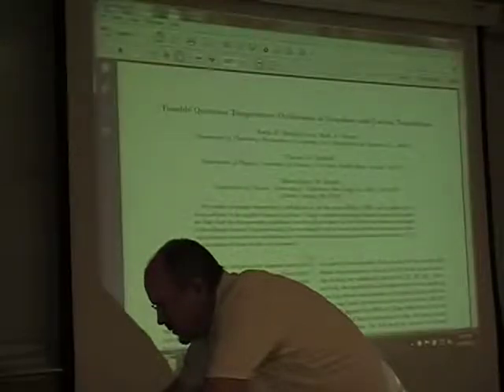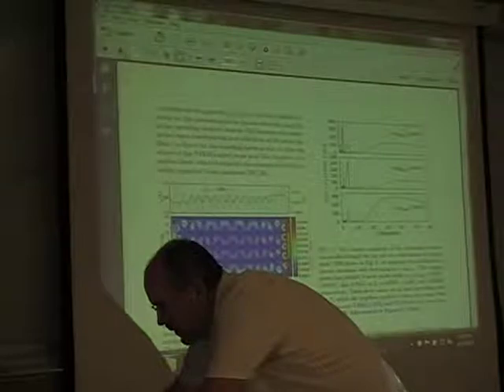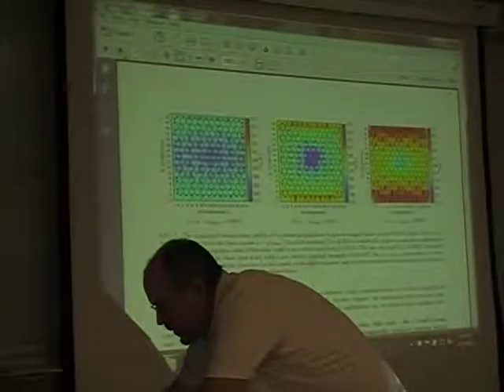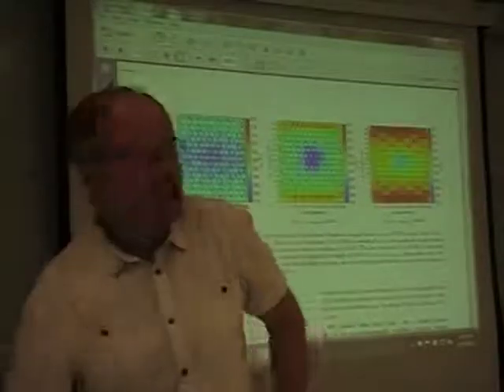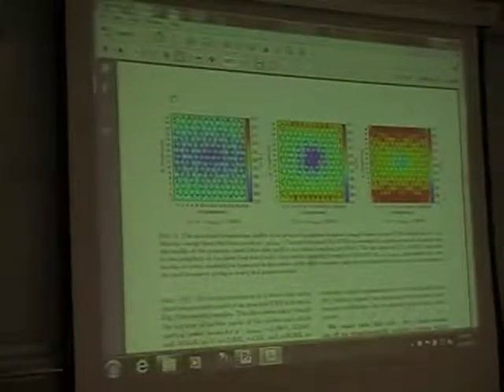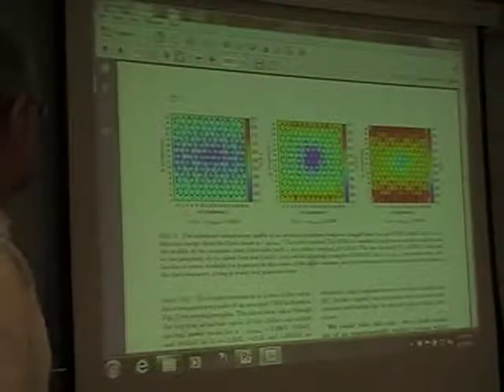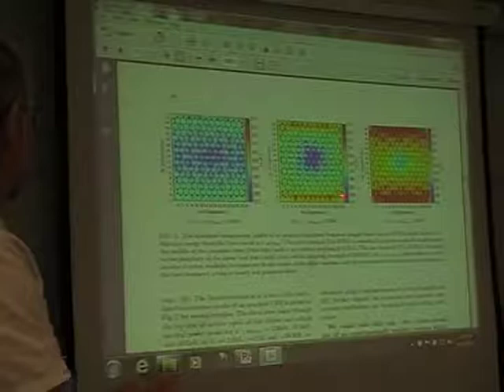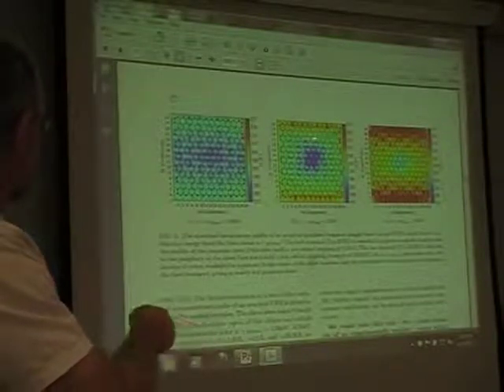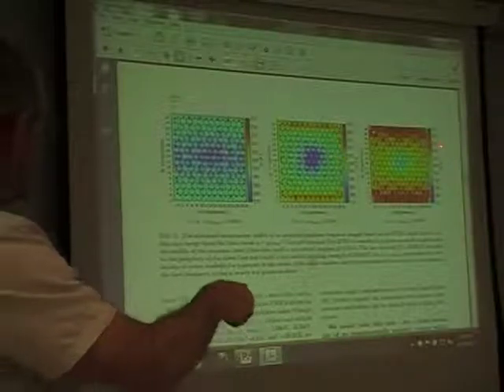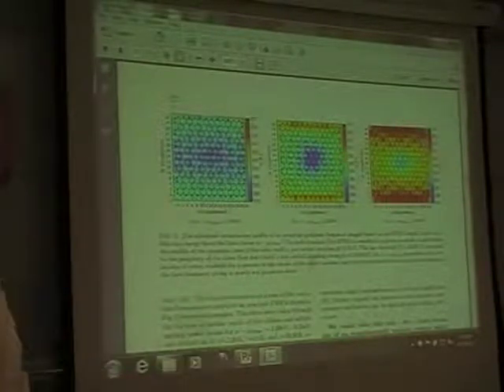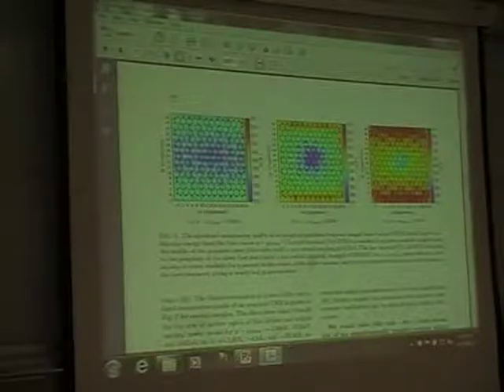What I was curious about is whether spin entropy would play a role in the zigzags. Oh, spin entropy, that's a good question. Okay, so here I have some results with a zigzag. And you see it's really quite different. Now here, it's like a cold contact in the center, right? And then there's a hot contact, the zigzag edges are heated. So you get a very different temperature pattern depending on the boundary conditions. But you would kind of expect that, right? Because there's a quantum interference effect which does depend strongly on the boundary conditions.